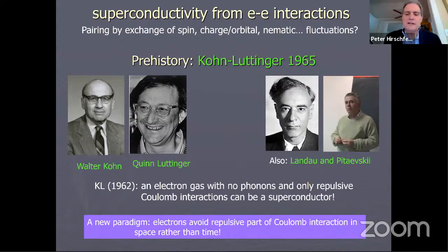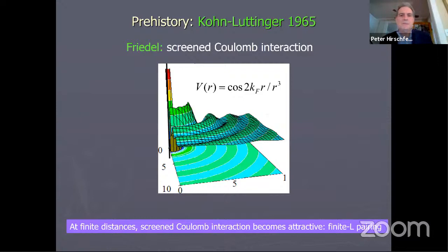And it's because there's a totally new paradigm. Retarded interaction is no longer necessary because the wave function of the pair avoids the Coulomb interaction in space rather than time. And the way this works is, this is a picture of the so-called Friedel oscillations in a metal. Let's imagine that you put an electron at the origin of the coordinate system here at 0, 0. That's this big peak in the effective potential due to this electron, or due to this charge, in the presence of the electron gas. And it falls off in three dimensions like 1 over R cubed, but it oscillates and it changes sign. So the projection into the plane here shows that there are stripes of different sign potential.